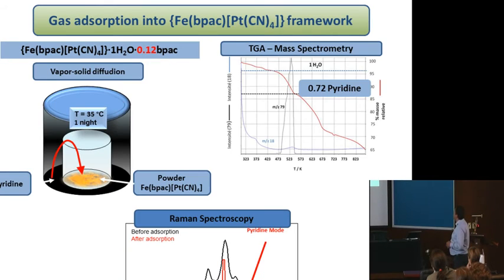Okay, so to go further, we expose these powder complexes to vapors of pyridine. We let the sample sit overnight at 35 degrees. And we check the uptake of the pyridine using TGA coupled mass spectrometry and Raman spectroscopy. Using Raman, again, it was possible to see the inclusion of the pyridine. And using the TGA coupled mass spectrometry, it was possible to estimate that we have about 0.7 pyridine per iron center.